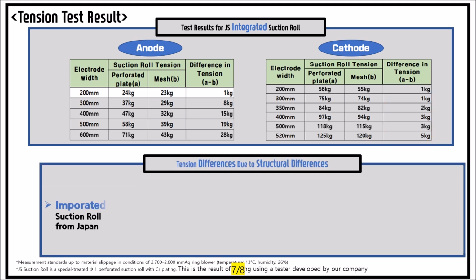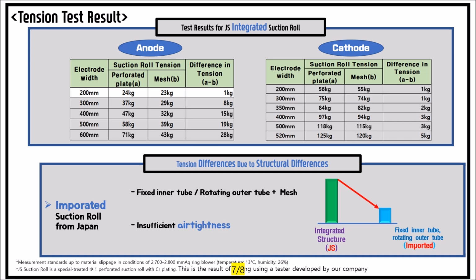For reference, the suction roll imported from Japan, which features a structure with a fixed inner tube, rotating outer tube, and mesh covering, has been measured to have approximately 30% lower tension than our suction roll due to its lack of air tightness. In summary, the perforated plate type maintains high tension, demonstrating excellent performance in material feeding and tension cutting, making it highly effective even under high tension control conditions.